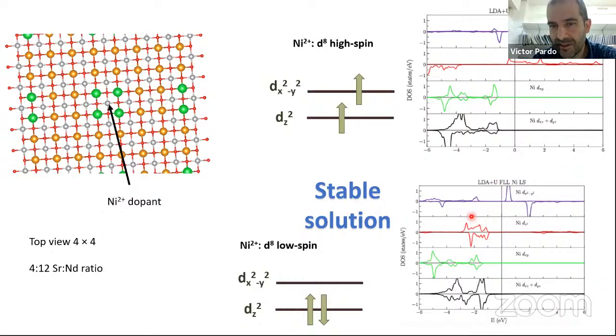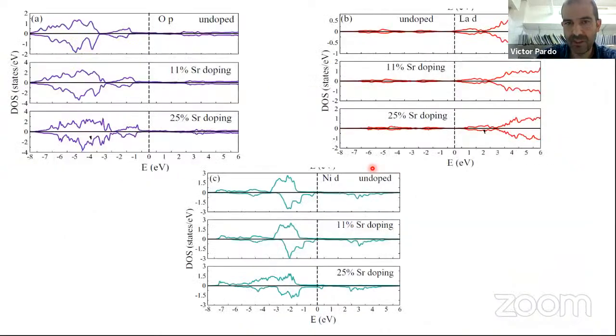We see that the difference between the low spin and the high spin is the involvement of the nickel dz². In the high spin solution, which is not stable, you would have a strong appearance of the dz² orbitals at the Fermi level, which is quite contrary to the physics of the cuprates. Whereas in the low spin energetically favored situation, the dz² orbitals are fully occupied, and around the Fermi level you have this single dx²-y² band that is the one that appears in the cuprates. So it seems that doping brings the system closer to the cuprates.